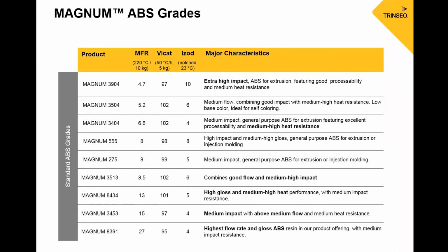So here I'm going to go through a list of our standard ABS grades, and this is showing information based on melt flow rate, MFR at 220C and 10 kg, and the VICAT softening temperature, as well as the notched IZOD impact resistance. So we have a range. This is listed in order from lowest to highest melt flow rate. And we have a wide range of products with the lower melt flow rate, which is a single shear rate rheology data point. I'm sure most of everyone on this call knows what melt flow rate is, but some may not, so I just wanted to explain that a little bit.